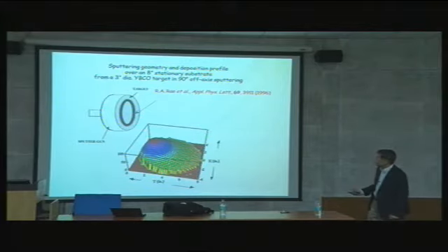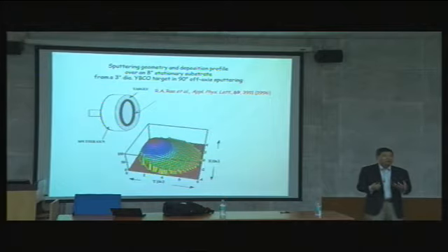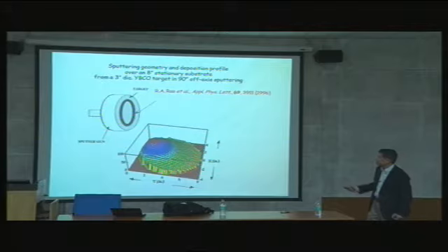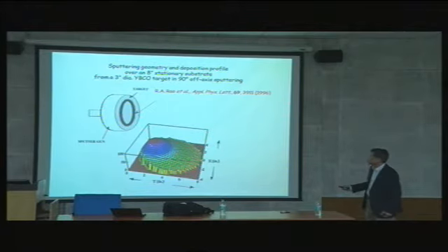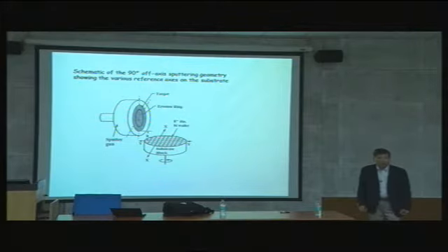This is the profile of off-axis sputtering, a thickness profile. It's not a composition profile, it's a thickness profile. Composition is a lot more forgiving than the thickness profile. So composition here is not much different, but thickness drops a lot here. In order to overcome this, we do a measurement of the thickness across, for example, an 8-inch wafer area.